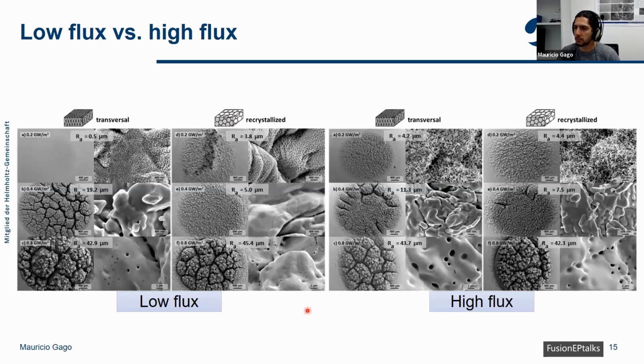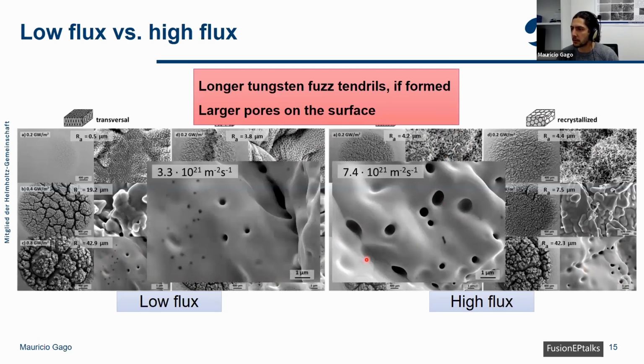So here we can compare them more closely. We see that at the lowest power load, for example, here and here, and here and here, between low flux and high flux, the fuzz formed is actually much higher, or at least much longer for the high flux samples. And at the highest power load, if we compare the size of the bubbles or the pores that are being formed, we can see that the pore size is much larger with a higher flux. So this means that if the fluence is several times higher in ITER, the pores could be expected to be even larger. So this is also an important factor to take into account when we want to analyze how the material will behave.